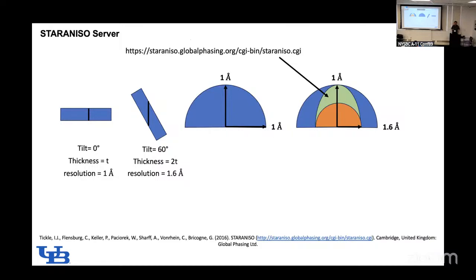And I'm going to just talk about one thing that Tim touched on before I kind of end. This is a weird phenomenon with electron diffraction. I'm going to pitch using the STARANISO server for all of your data. For us, this ends up being critically important. The reason being is at tilt 0, your crystal has a thickness T in the microscope, and it looks beautiful. It diffracts to 1 angstrom. You now tilt it to plus or minus 60 degrees so that you can collect your data. At 60 degrees, your sample is twice as thick, and now it diffracts to 1.6 angstroms instead of 1 angstrom.